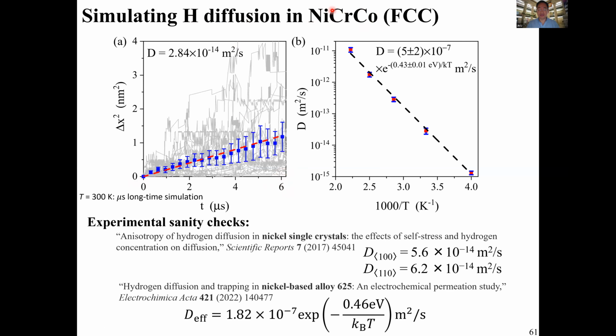But also, this has so-called chemical short-range order. So we're doing this hydrogen diffusion in a pretty large supercell in order to study this medium-range, chemical short-range order effect. Now, we do not know whether our prediction is correct or not. So at room temperature, it's about 10 to the minus 14 meters squared per second.